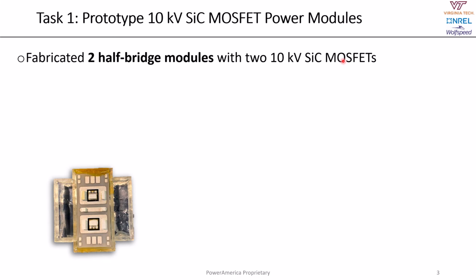Shown here is the bottom half of one of the 10 kV silicon carbide MOSFET modules, where you can see here the two 10 kV silicon carbide MOSFETs. They're in a half-bridge configuration. And we use sintered molybdenum posts instead of the wire bonds for the interconnect.